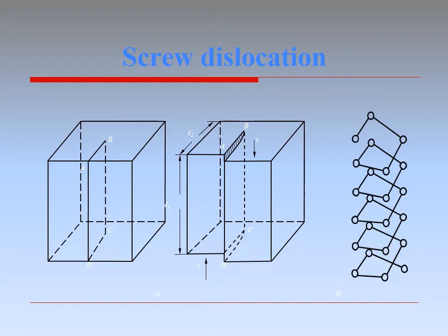This figure shows the arrangement of atoms in two vertical planes passing directly on either side of the shear plane ABCD. The resulting shift of the described area of imperfection is called a screw dislocation. The atoms are arranged like a spiral staircase. Screw dislocations, as well as screws, can be left and right. They are mirror images of each other.